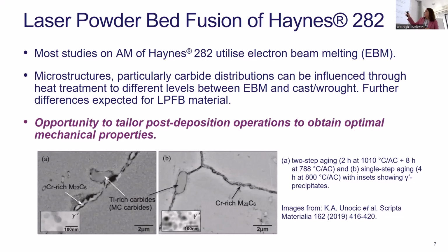So in this study that I've included here by Christofidou, Microstructural, we've got a couple of different heat treatments. On the left is the two-step aging that's recommended by Haynes, which results in some large titanium-rich MC carbides with M23C6 at the grain boundaries. And what they were looking at was how they can influence that or achieve that without having the multiple steps. And what they found was actually they can just create a very similar microstructure with just 4 hours at 800 degrees Celsius. So that suddenly changes a lot of the dynamics of our microstructural optimization. So that gives us an opportunity to actually tailor the microstructures using post-deposition operations to obtain optimal mechanical properties, rather than just looking at the build alone.